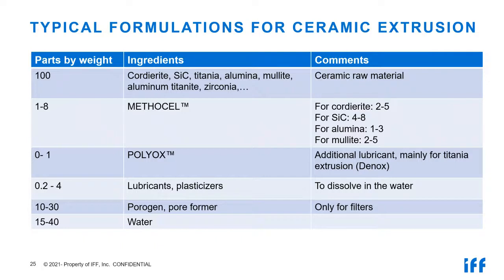An additional lubricant is Polyox, which is used nearly in all cases if you extrude titania honeycombs for DeNOx filters, but it is used also in other extrusion applications, and it is an additional lubricant leading to a wonderful plastification of the mass, and it has not a big effect on the gelation temperature. Further lubricants are used more or less everywhere. You can read a lot of literature about the further lubricants and plasticizers. Please use them only as much as needed, because a higher amount always leads to problems in the cohesion of the ceramic particles, and also they contribute to a reduced gelation temperature. So it's always a compromise, as much as needed, but not more.